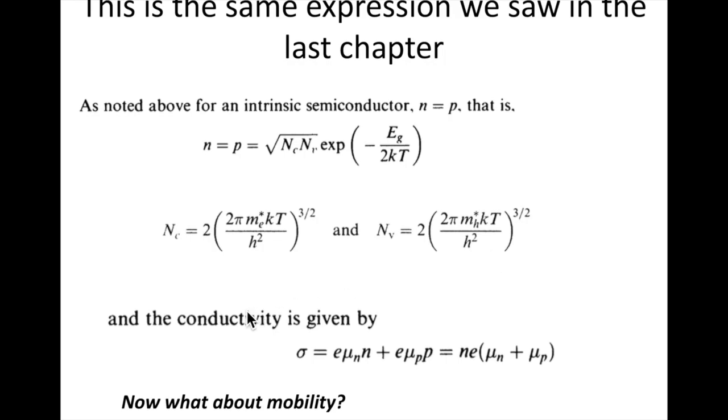And so doing that, we can then get conductivity. So here is the conductivity for electronic conductivity, right? So the charge, mobility, and then the concentration of our species. So n for electrons, p for electron holes. And so that's sort of the sum here. So we've looked at how we get the concentration, and you see that the concentration of these species is temperature dependent.